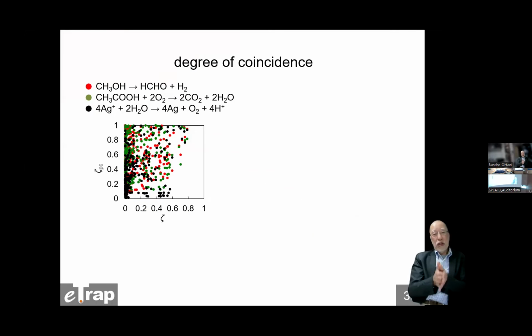And then we checked a very large number of titanium oxide samples by pairing those titanium oxide samples. In this plot, the x-axis is the zeta value of pairs of titanium oxide. So 1 means almost the same. 0 means completely different. And the y-axis is the photocatalytic activity for those 3 kinds of reaction, including hydrogen evolution, carbon dioxide evolution, and oxygen evolution. And they are plotted.